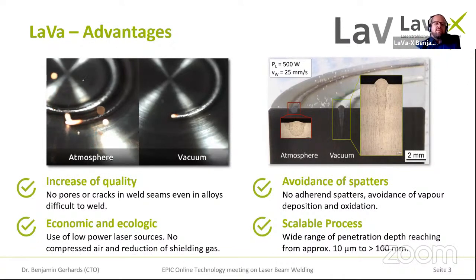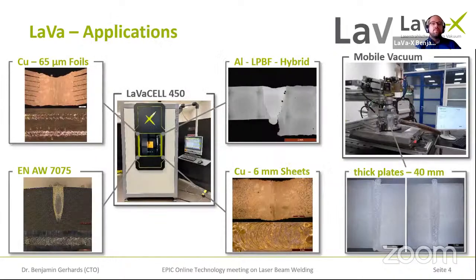Typical applications, next to welding of stainless steel, where we have very high qualities, and welding of titanium, are the typical materials used in e-mobility, so copper and aluminum materials. You can see in the upper left picture, we welded copper foils with a thickness of roughly 65 microns, and this is possible with a laser power lower than 1 kilowatt. As Michael from IPG said, we do not need any blue or green laser beam sources. We can do it with our IR lasers as well. And we can also reach a penetration depth in copper of 6 millimeters, and we roughly needed 5 kilowatts of power for this.